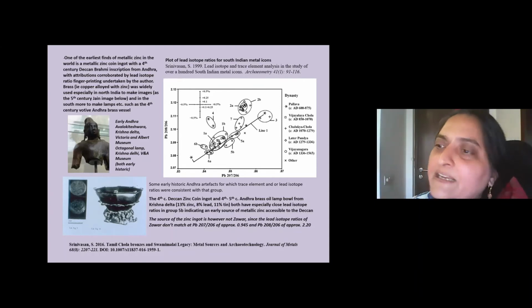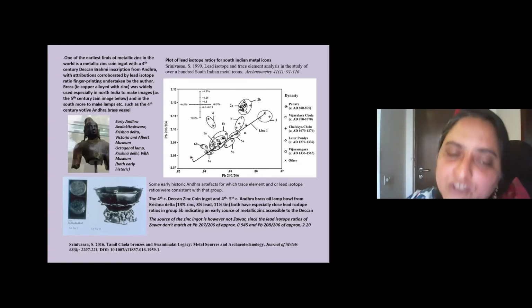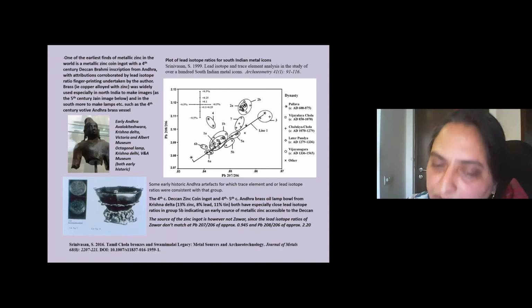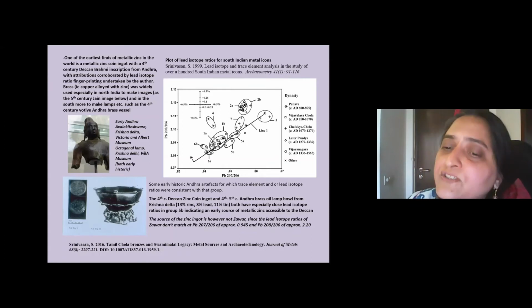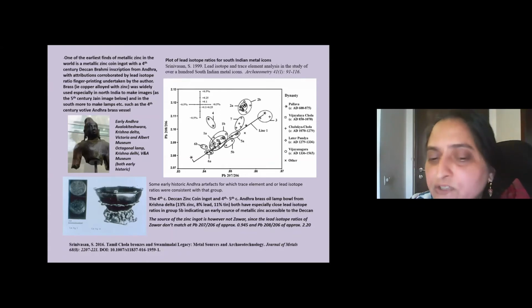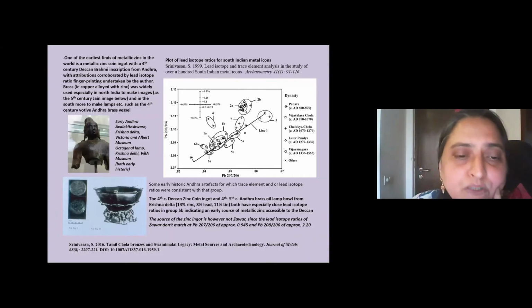And of course, if we had the lead isotope ratios of the ore sources, we could actually identify the source, which in this case was not easily possible. But what was interesting was that the zinc ingot that I showed you also matched the lead isotope ratios for a 4th century Andhra oil lamp of the Krishna Delta, which was a brass artifact with 13% zinc, 8% lead, and 11% tin. And so that suggests that, apart from Zawar, because these ratios did not match Zawar, since Zawar falls in a completely different area when you do the plot, with Pb 208 versus 206 closer to 2.2 and so on, this was not Zawar, but seems to be another early mining source and source for extraction of zinc, which seems to have been available in South India, though we don't quite know where that was.